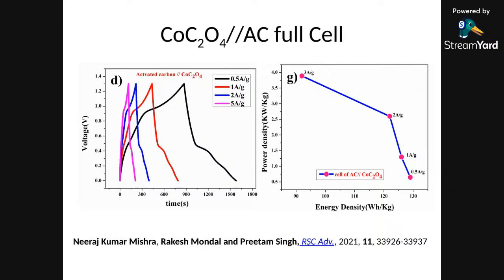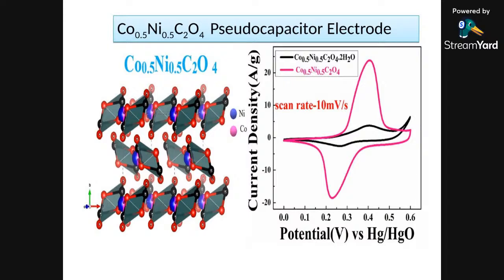So this is actually coming as a new structure family where a lot can be done by tuning of the active redox ion and using the oxalate framework. Further, we have extended our work and we have made the doped material, meaning cobalt and nickel both we have intercalated together. Even though nickel has shown a little lower performance, nickel has shown very high intercalative behavior. So when we have made this together, you can see from this CV, compared to the hydrated one, the non-hydrated is actually performing much better because a much more porous structure is created using this anhydrated oxalate. And the redox peak is completely intercalative. And if you see the flat part, which is more like a capacitor plot, it is also much higher than the hydrated one.